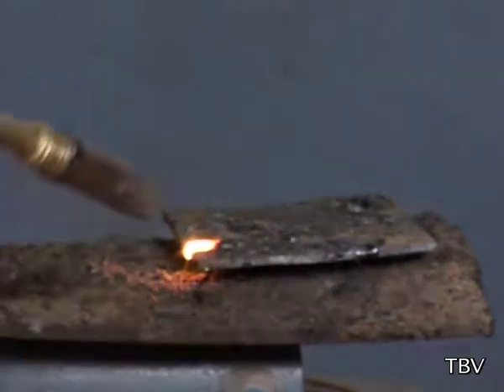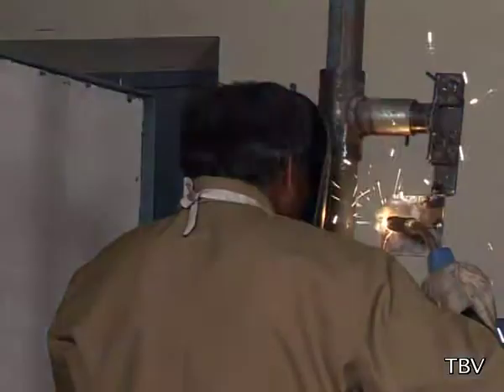Hold the gun perpendicular to the joint and strike the arc at the tack. Move the torch from left to right end of the joint in horizontal position. Maintain the angle of the torch at 10 to 15 degrees towards the direction of travel throughout the weld length. Deposit the root run of the bead as shown.